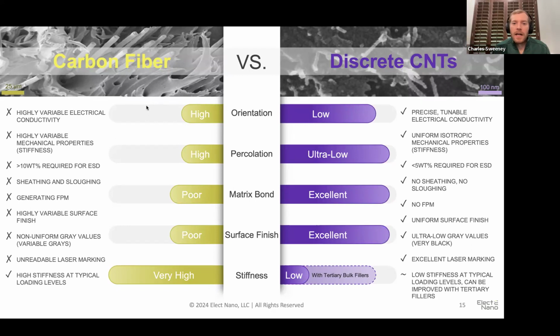And so one of the issues that has cropped up is that on average, the tray may meet the electrical property requirements for surface resistance to be ESD-safe, electrostatic discharge safe. But if you zoom into the scale of the computer chip, it sees areas of overly conductive, like pointy ends of a lightning rod sticking up out of the plastic, or insulating areas between the plastic, or areas where the carbon fibers are aligned or randomly oriented. And this can create a lot of variability in the electrical properties.